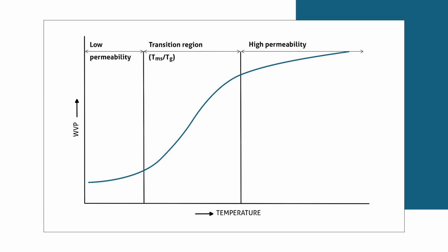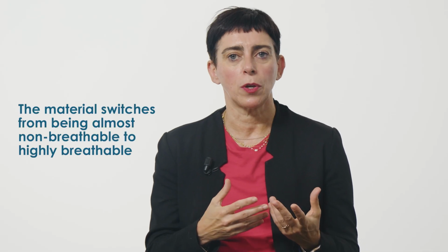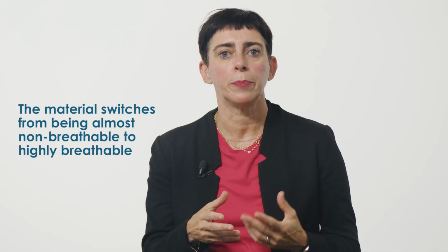In material science, this natural strategy has been copied to design thermosensitive membranes. In the figure, you can see how water vapor permeability of one of these membranes increases sharply at a specific point. That point is the glass transition temperature of the material. It's the moment when the polymer shifts from a rigid, glassy solid to a softer, more elastic state with extra free volume. In simple terms, the material switches from being almost non-breathable to highly breathable just by tuning its porosity with temperature.